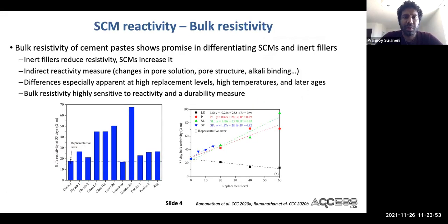What we have shown is that bulk resistivity can be used to differentiate SCMs and inert fillers. The reason for this is that inert fillers, especially at later ages, reduce the bulk resistivity. On the other hand, reactive supplementary cementitious materials increase it. This can be seen, for example, in this figure here. So this is the control. All the SCMs that you have are increasing the bulk resistivity. On the other hand, the limestone is decreasing it. Now, this is especially true as you increase the replacement level, because for reactive materials, the bulk resistivity increases as the replacement level increases. For fillers, it reduces.